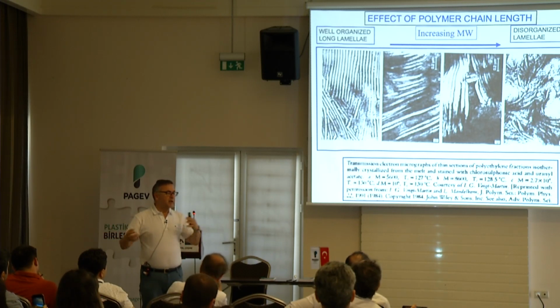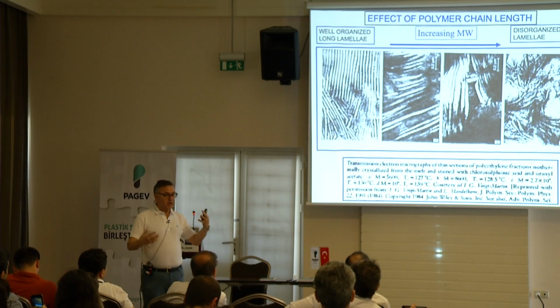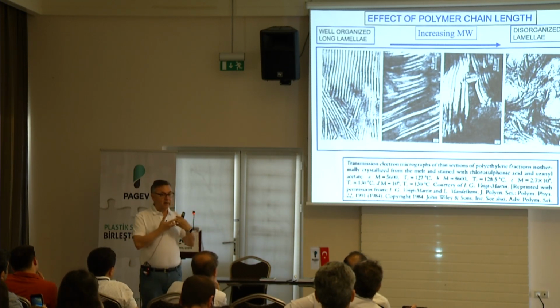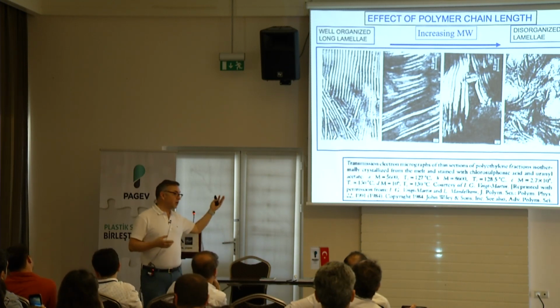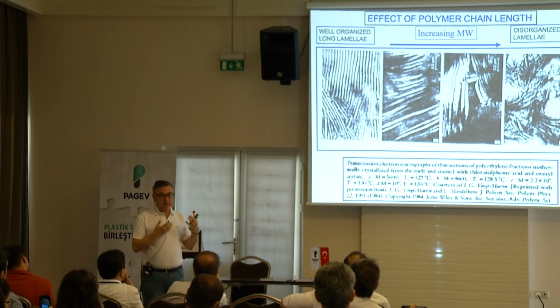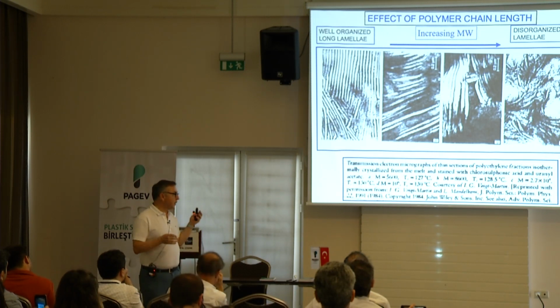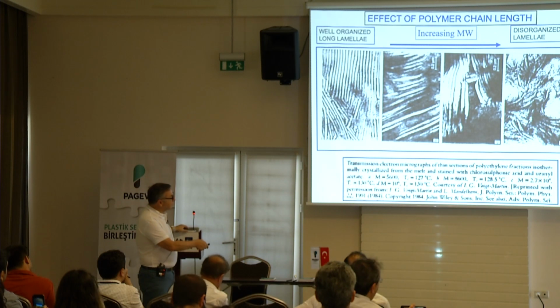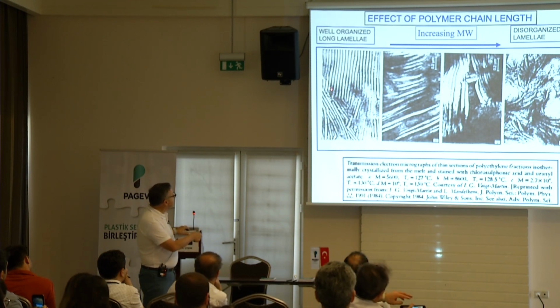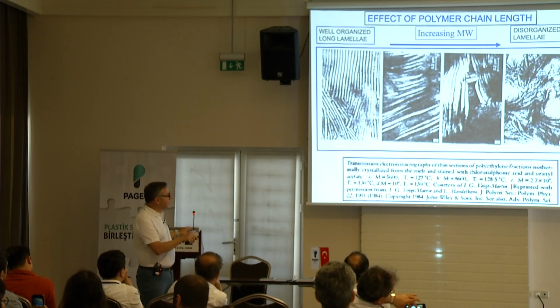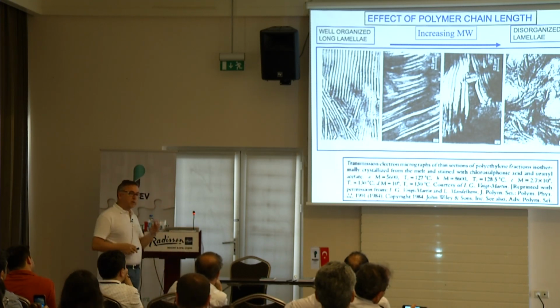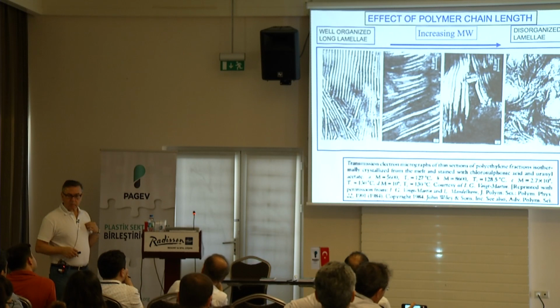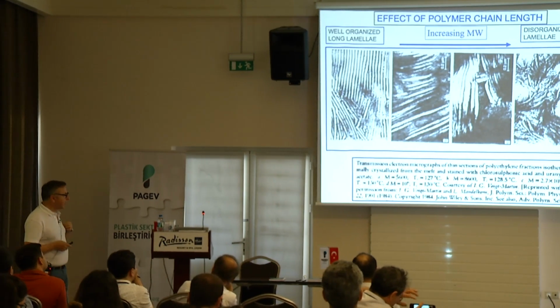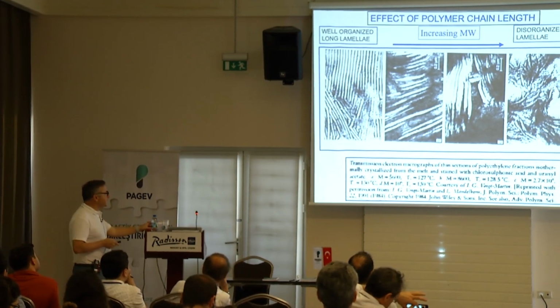You have an ability to crystallize faster maybe because long chain molecules can entangle in the melt, but ultimately all these entanglements is going to be problematic in terms of quality of crystals. See, the short chains, they make a much better looking lamella than long chains. So keep that in mind. So when you're blending, when you're doing compounding, these are important issues to keep in mind.